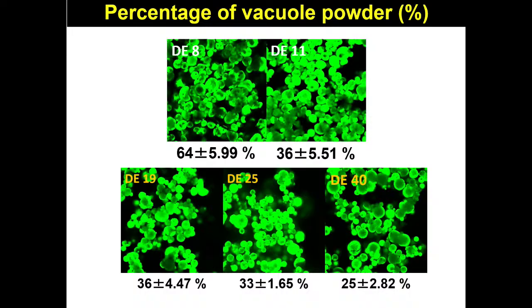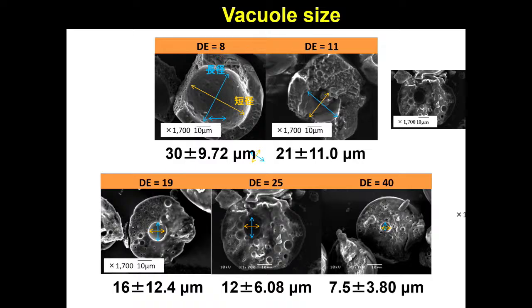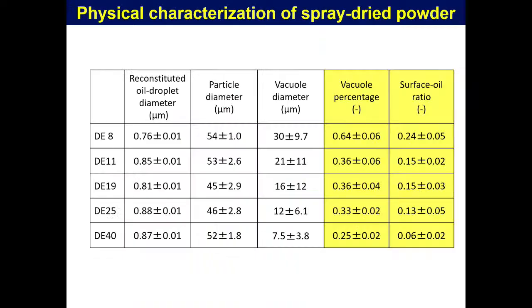And then in the DE 8 case, about 64% of powder has a vacuole. But in the DE 40 case, 25%, a small amount of vacuole. And also, in the DE 8 case the vacuole is 30 micrometers, and in the DE 40 case, 7.5 micrometers. So dextrose equivalent affects the vacuole size because DE affects the film formation rate. So for DE 8 and DE 40, the vacuole percentage and surface oil we can see in this kind of table.